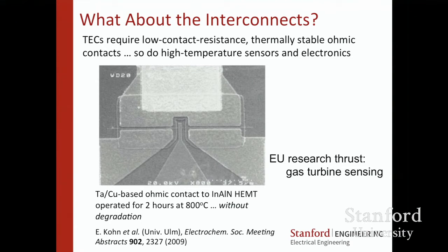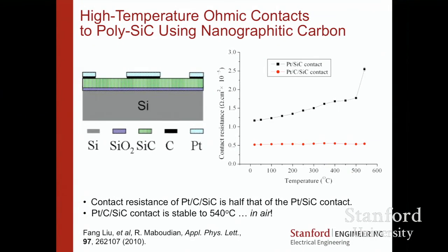My students sometimes anneal things in furnaces at 800. This thing's operating at 800, and it has a very modest tantalum copper ohmic contact. I don't show the one in this Electrochemical Society paper where the metallization was screwed up and didn't work. It was completely destroyed operating at that temperature. So actually these materials could be not so much of a problem.